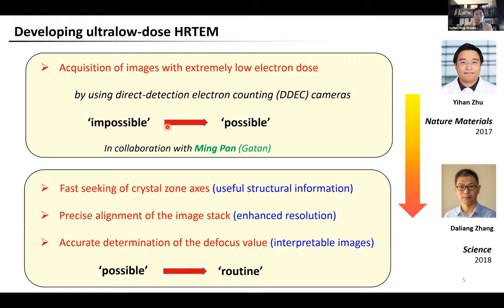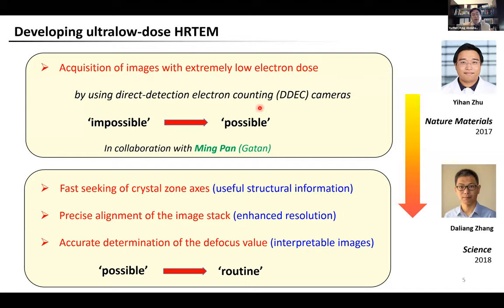In the first step, we collaborated with Dr. Ming Pan from the Gatan company and demonstrated that a new type of camera — the direct detection electron counting camera — is sensitive enough to produce images at the ultra-low-dose conditions required by MOFs. In the second step, we developed methods to further improve the efficiency and quality of HRTEM enabled by this new camera. So the first step is about new hardware, a very sensitive camera, and the second step is about software to solve practical problems related to low-dose imaging. Taken together, we are now able to use HRTEM to study MOFs at atomic resolution.